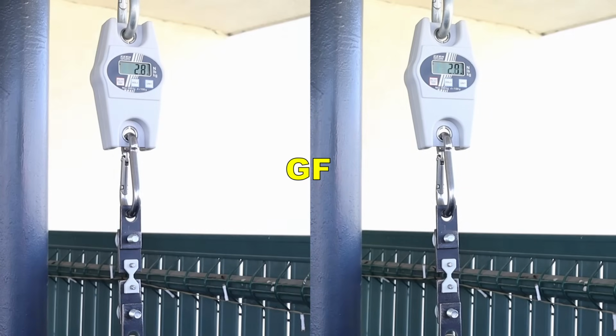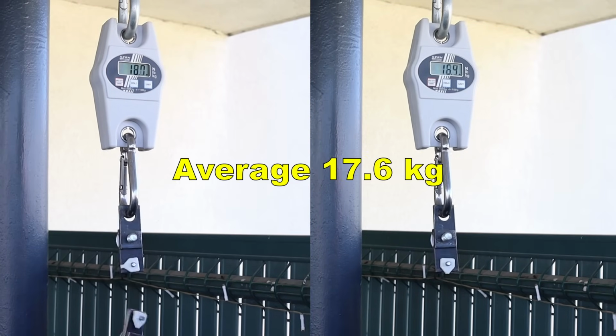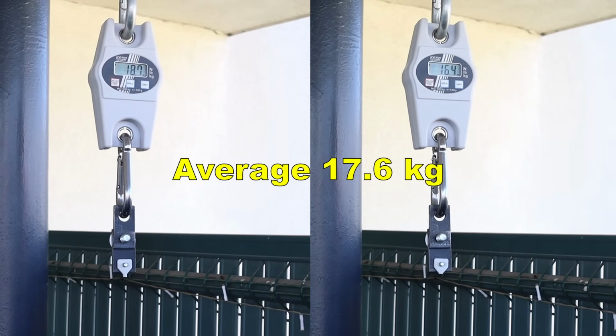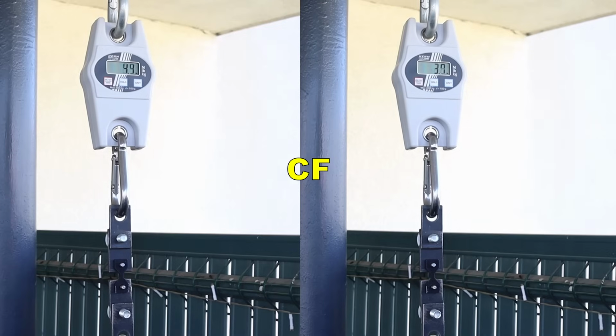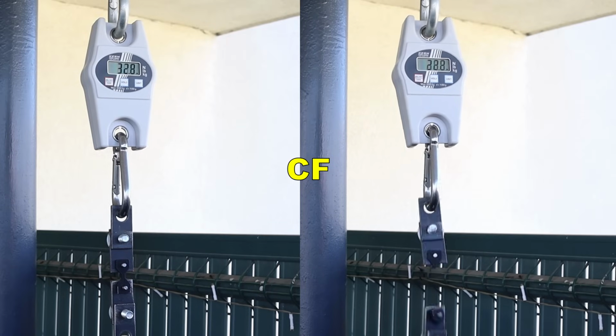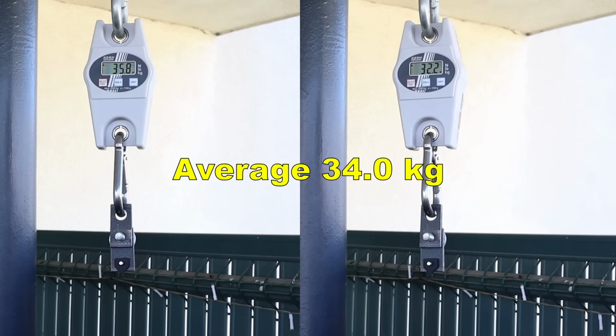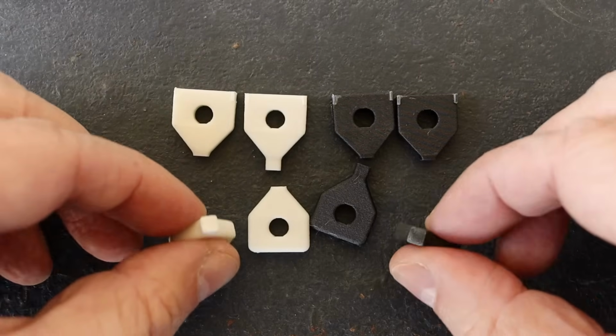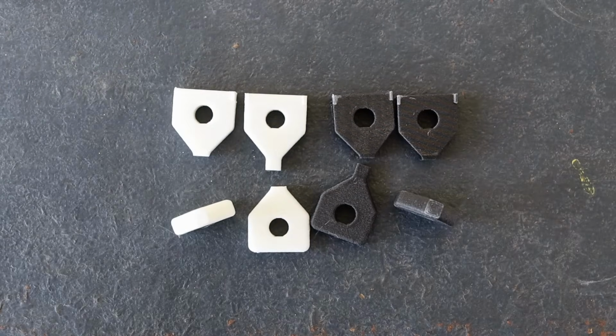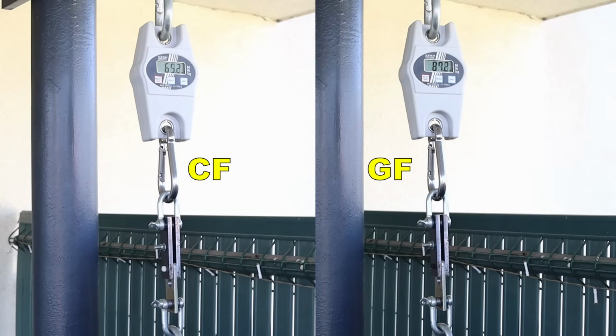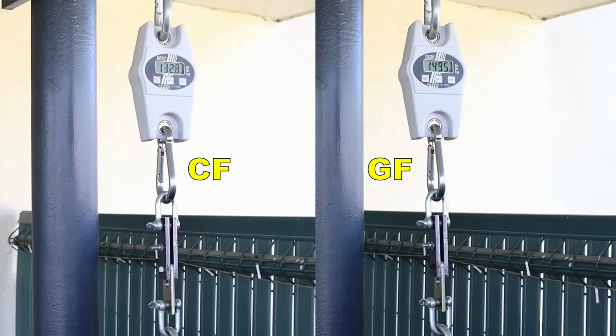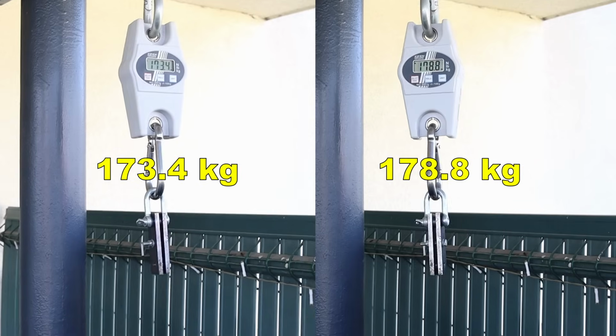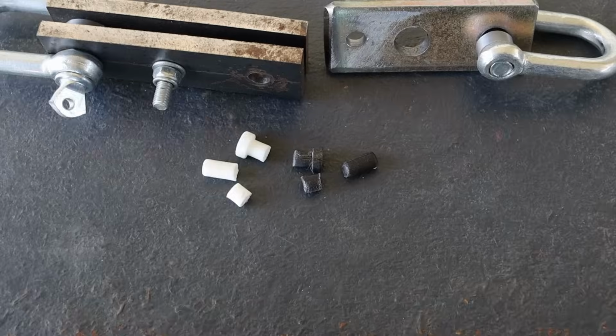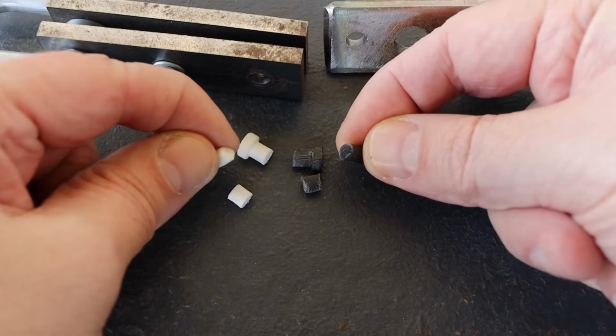And then the layer adhesion test. These test objects are printed in vertical position, and this is quite low break load on the glass fiber filament. Now let's see the carbon fiber version. 34, this is really acceptable, especially that this is reinforced with carbon fibers. And now two-sided shear stress. In both cases those fibers really help. Over 170 kilograms is the break load. Break correctly in 3 pieces.